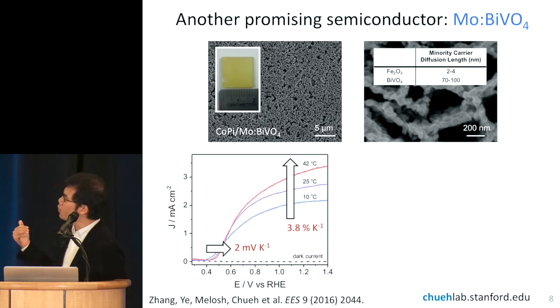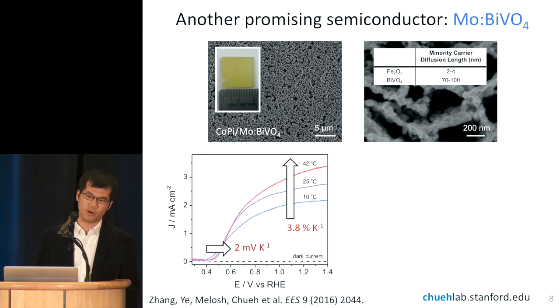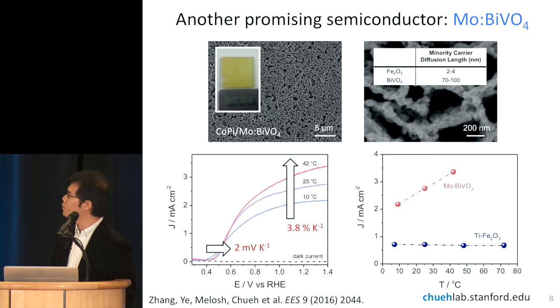And the shift in the voltage is only about 2 millivolts per Kelvin. This is a really impressive performance because the loss in voltage is relatively small compared to the gain in current. So on a net basis, you're getting more photopower out of this system. And if I compare this to the iron oxide example on the previous slide, we have an almost flat line showing that 1% behavior in iron oxide, but the red line I showed for bismuth vanadate is now up to 4%.